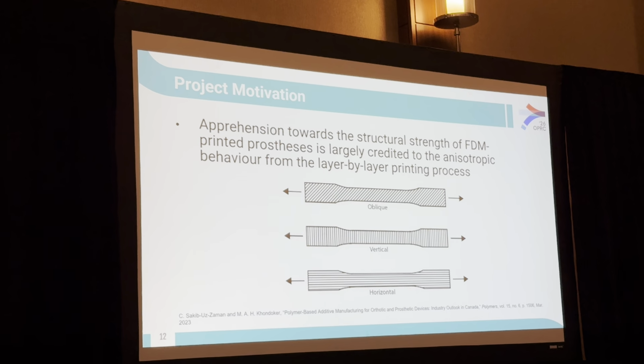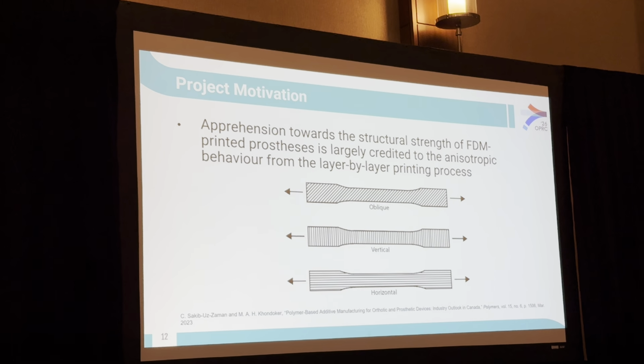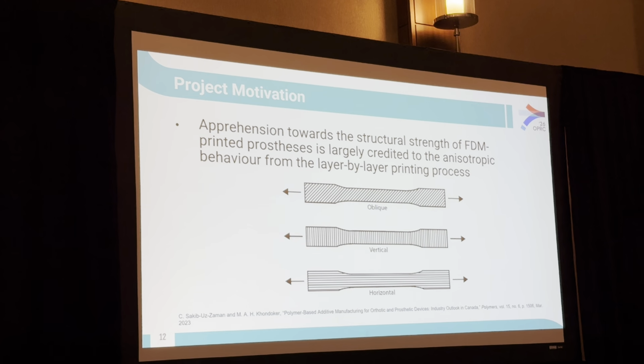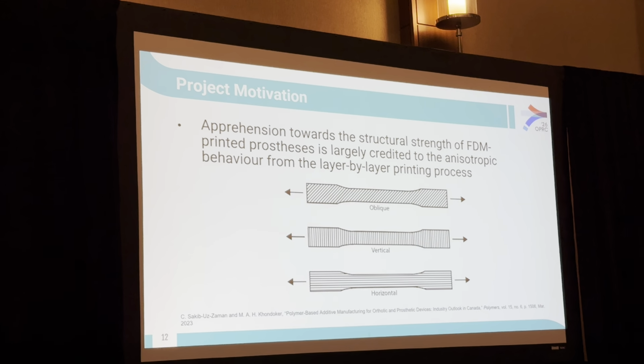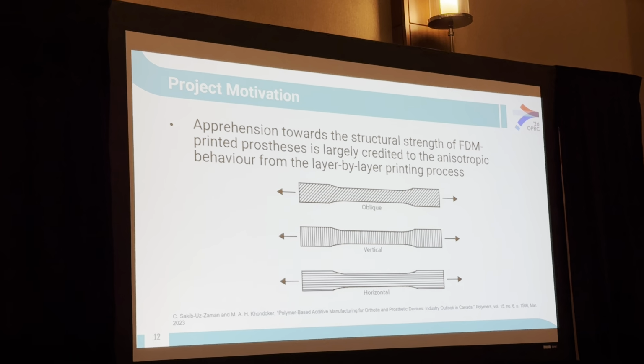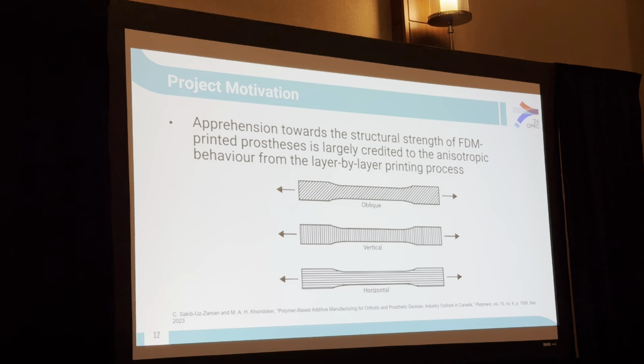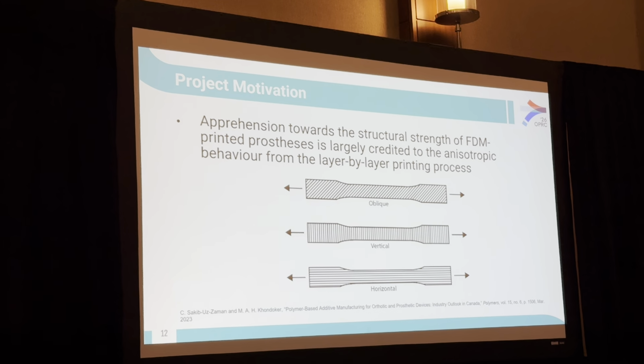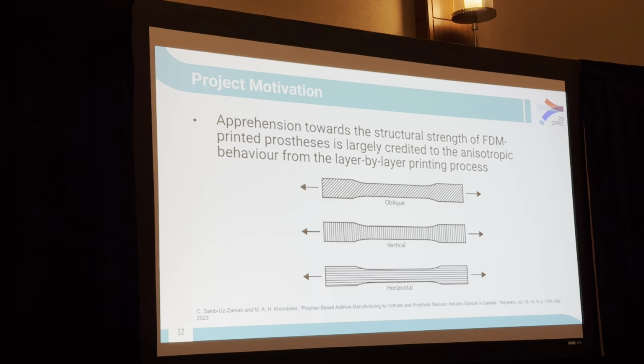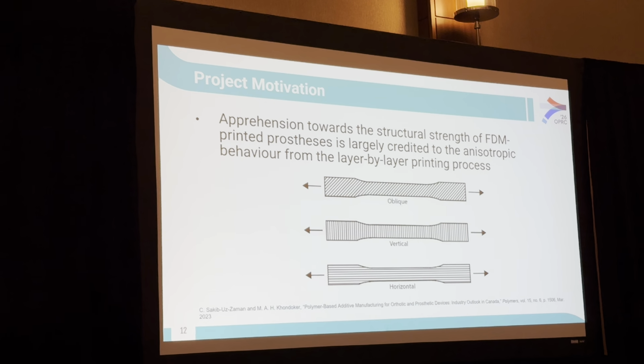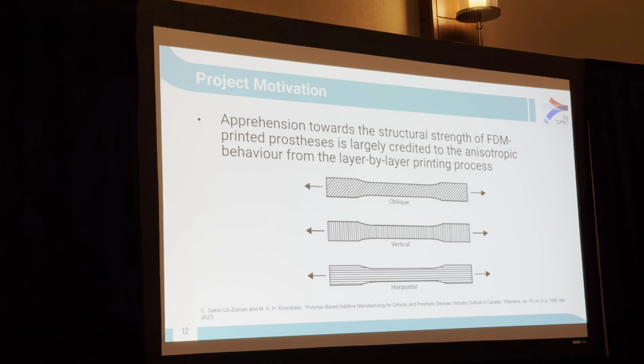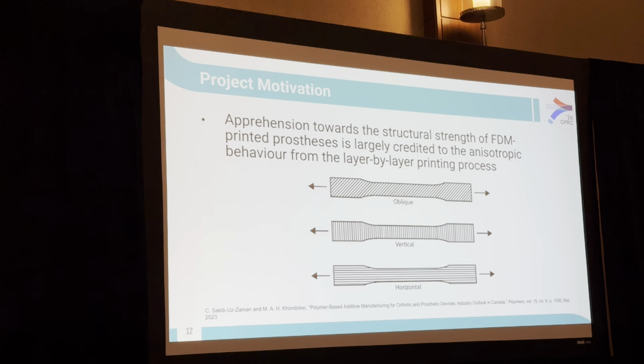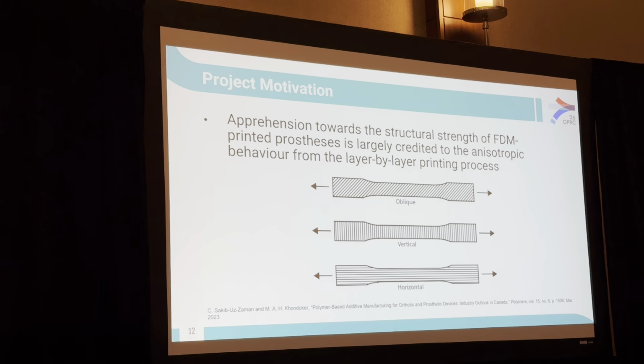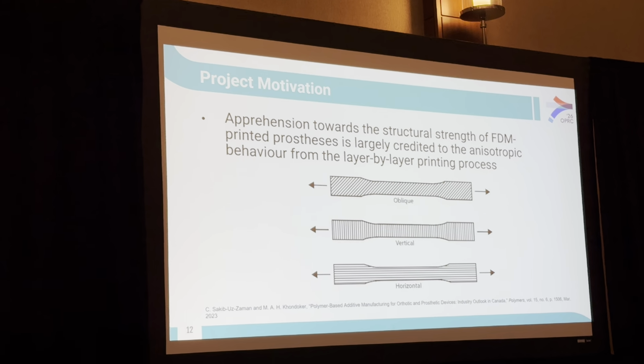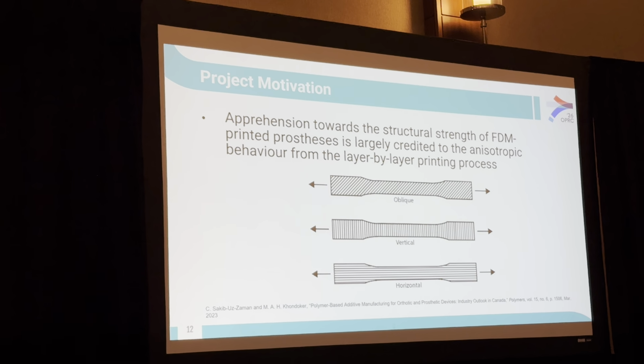Here I want to illustrate and further explain what I mean by directionally dependent behavior. If you look at the bottom image here, this horizontal material specimen, the load is applied in the direction shown by the black arrows, parallel to the filament strands, which means the strength relies on the filament strand itself. However, if we look at the vertical sample in the middle here, the load is applied perpendicular to the layer lines, so the strength then relies on the quality of the bond between the filaments rather than the filament itself. Therefore, there are different material properties for the filament you're using based on the quality of the bond, not just the bulk material properties of that filament.